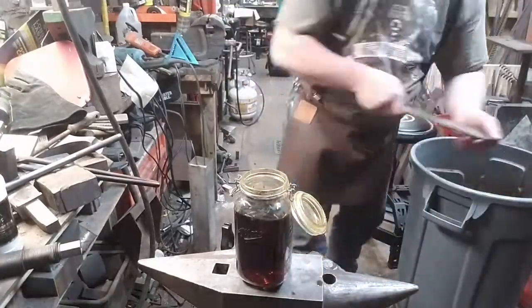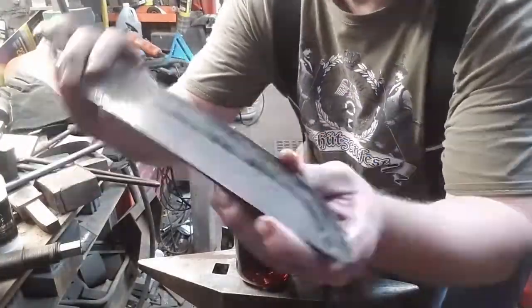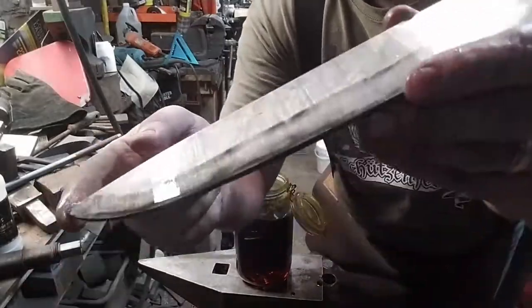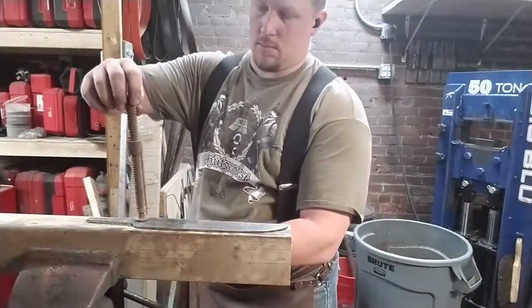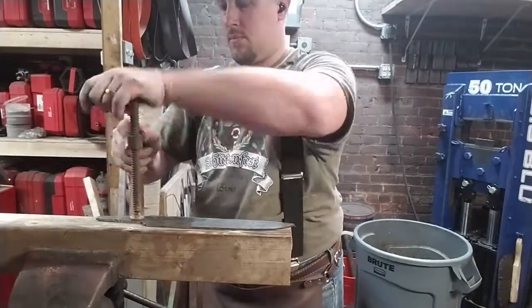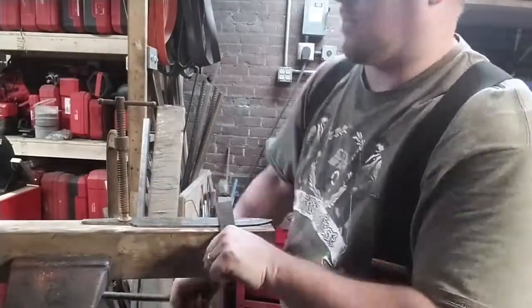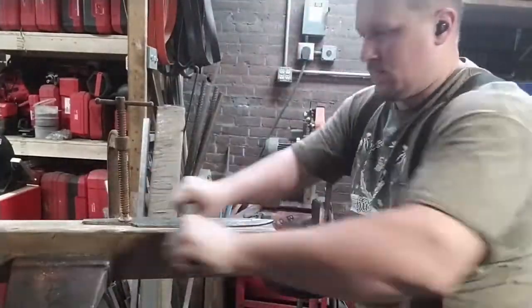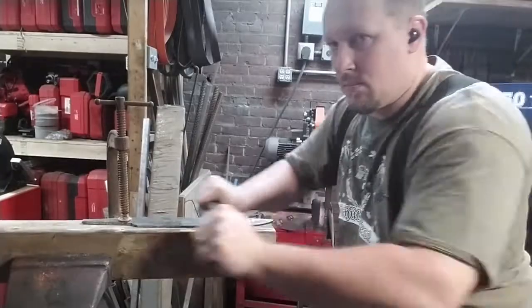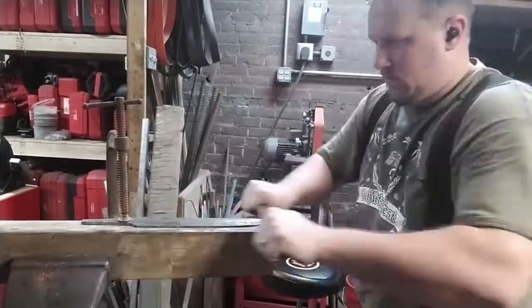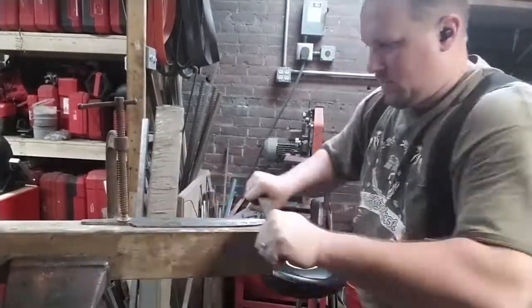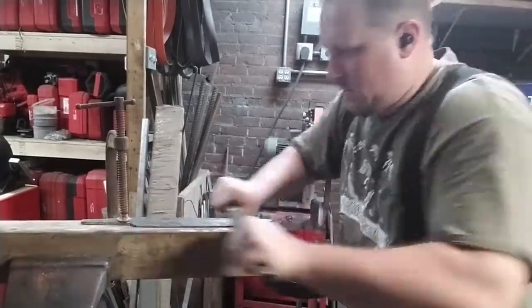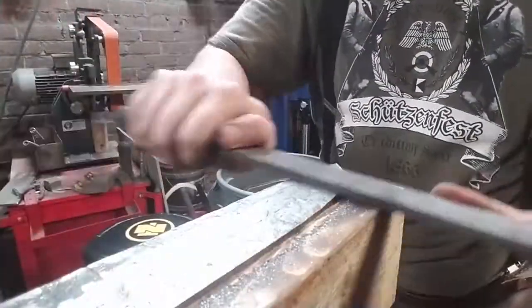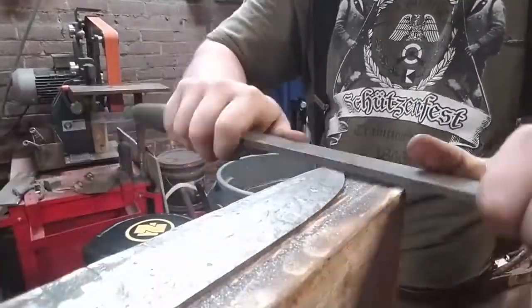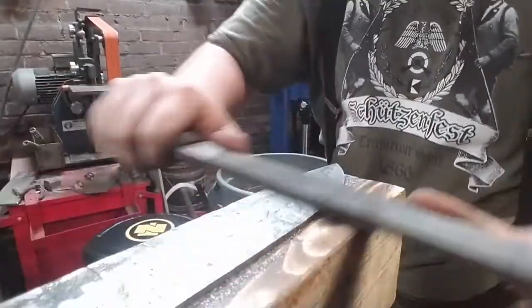So, as you can see, there's nothing. But when we flip it over, suddenly, there's a pattern. Now, it is very faint, that's true. But you can clearly see that there's such a difference between the surface as it was forged and the surface as it was ground. And that's because the process of decarburization has left the surface of the knife as it was rough forged as nearly pure iron. We can make steel with carburization, and we can make iron with decarburization.